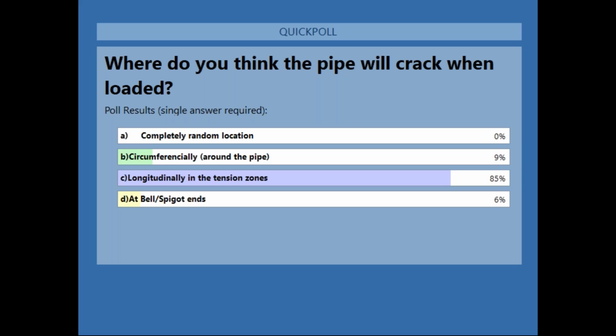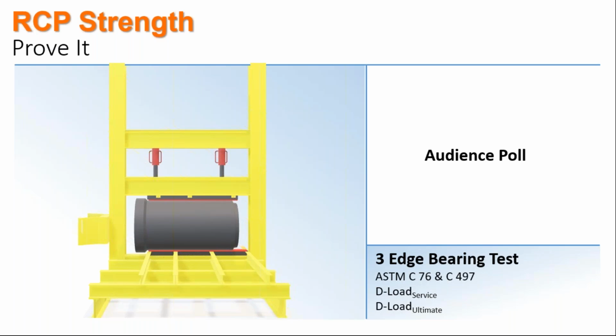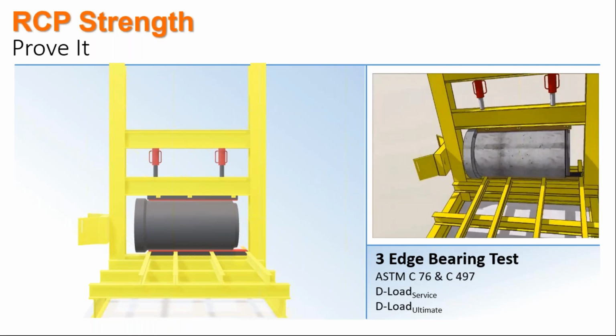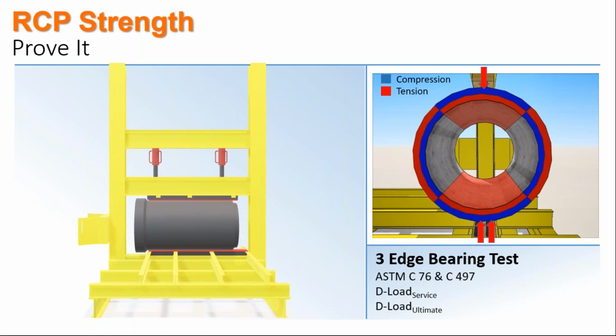Excellent. Well, thanks, Kim. So more than 80% of you got that correct. And we had a few folks that said circumferential cracks. By circumferential cracks, we mean a crack that runs around the outside wall of the pipe. If you take a closer look at the 3-edge bearing rack, the way those loads are oriented, it's actually trying to crack the pipe perpendicular to the span. So we would expect those longitudinal cracks in this situation.